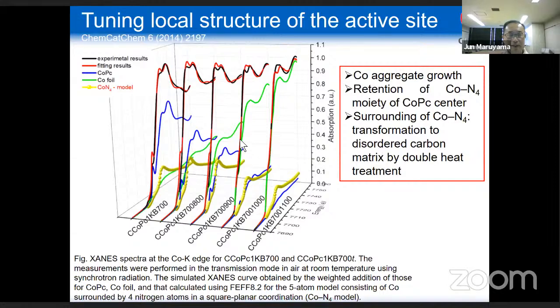This is a result obtained from X-ray absorption fine structure spectra. And this image shows the components of cobalt species. The content was changed according to the conditions of heat treatment, and optimized heat treatment conditions can produce a very active hydrogen evolution catalyst containing cobalt.